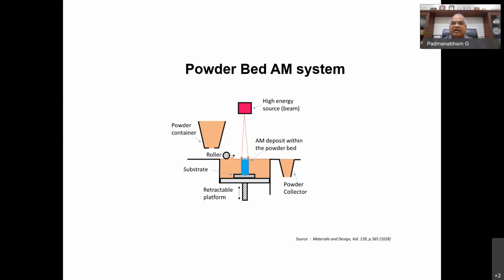Then after that layer, you lower the platform or the bed by about 50 microns or 60 microns, spread another layer of powder, again scan the laser beam, melt and solidify. Like this, the process continues layer after layer, and at the end you have a part that you are looking for. So this is called the powder bed additive manufacturing technique.